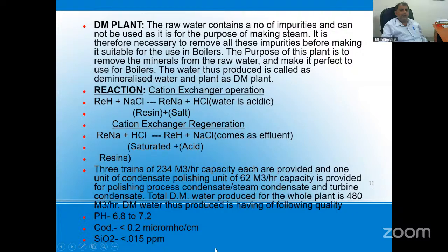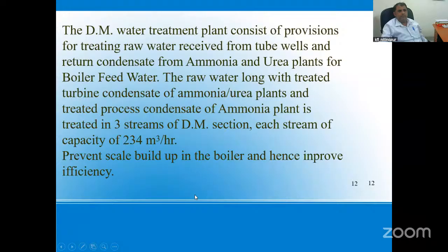DM water thus produced has the following quality: pH 6.8 to 7.2, conductivity less than 0.2 micromho per cm, silicon oxide 0.015 ppm. The DM water treatment plant consists of provision for treating raw water received from the tube well and return condensate from the ammonia and urea plants for boiler feed water. The raw water, along with treated turbine condensate of the ammonia and urea plants and treated process condensate of the ammonia plant, is treated in 3 streams of the DM section, each stream of capacity 234 meter cube per hour.